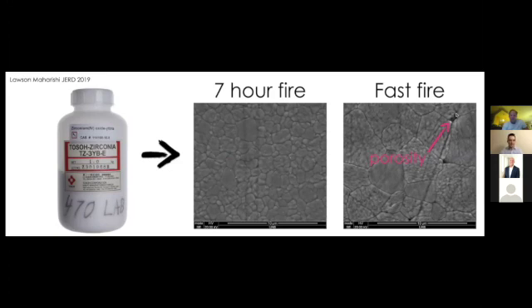So the thing with speed fire is, you just have to use the materials that, I don't know what the manufacturers did to make their materials able to be speed fired, but you just can't take any old zirconia crown and throw it in a speed fire and think you're going to get good results, because you get these wacky large grains and porosities if you throw the wrong kind of zirconia in there.